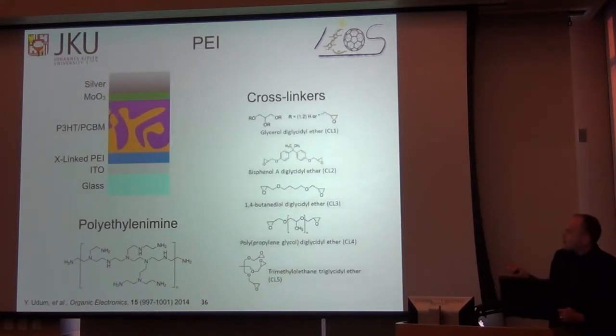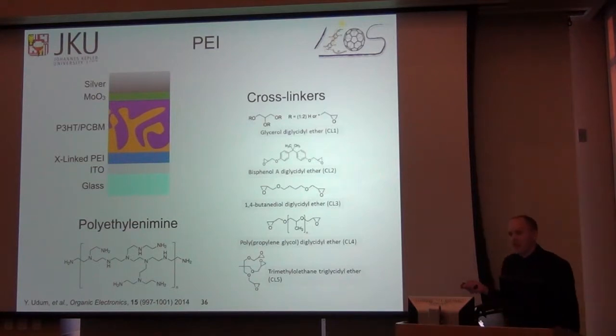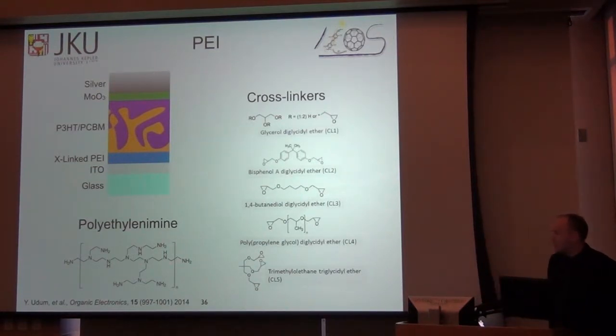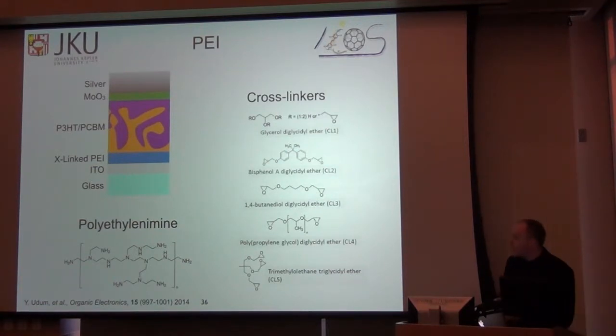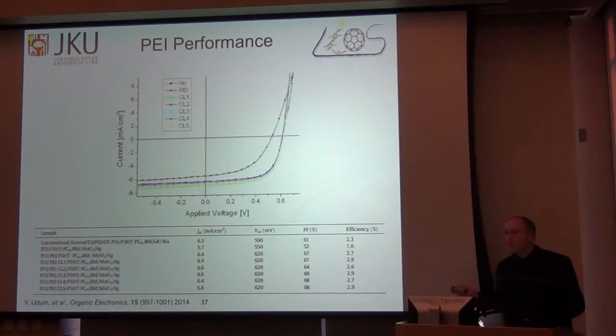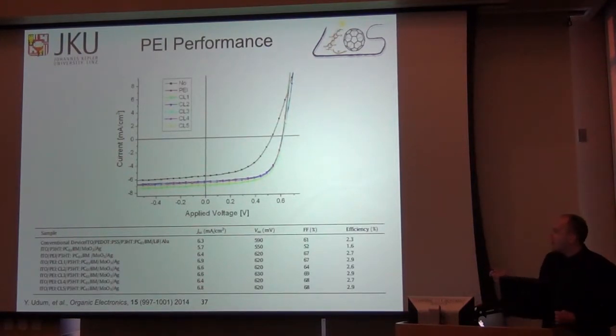More recently, we've used what's called polyethylenimine, which is an amine-containing polymer. And this is an insulator, so you have to put down a very, very thin layer, sub-monolayer, maybe 2 nanometers or less of this material. And we cross-link it onto the surface, and then we can subsequently solution process any layers on top that we want. We cap this with the molybdenum oxide silver back contact, and we wind up with a very reproducible way of making devices with very high fill factors.